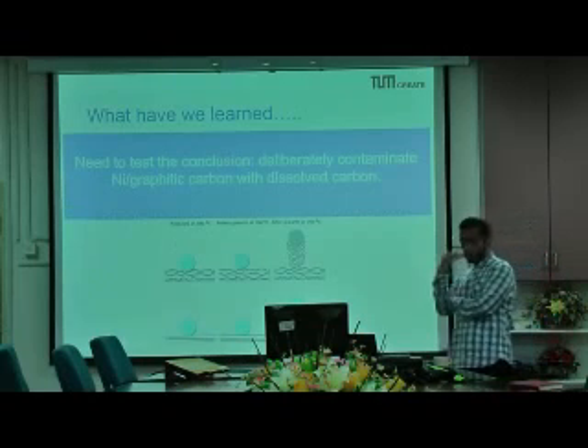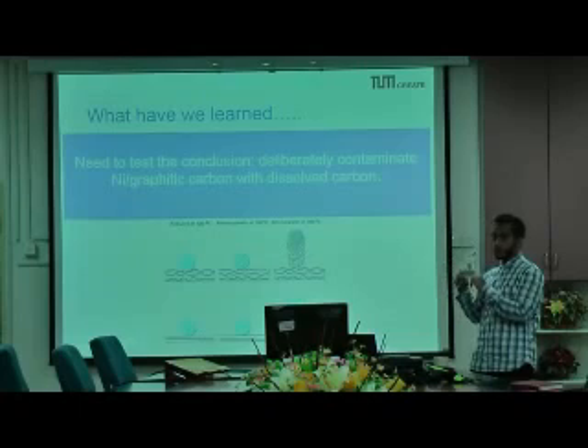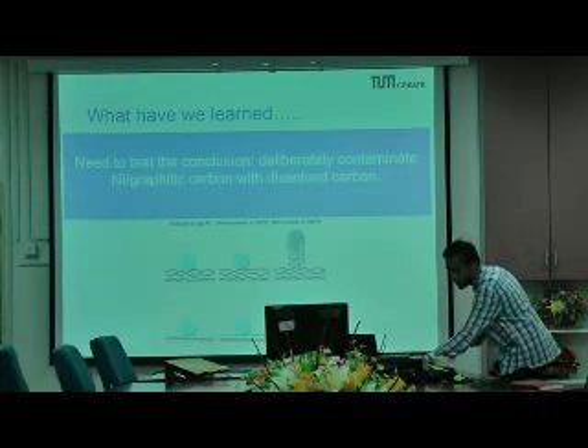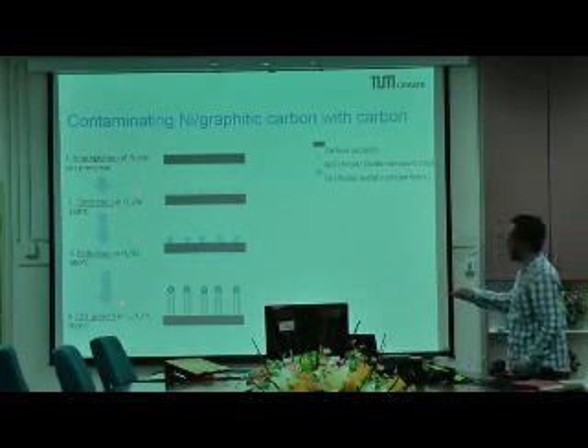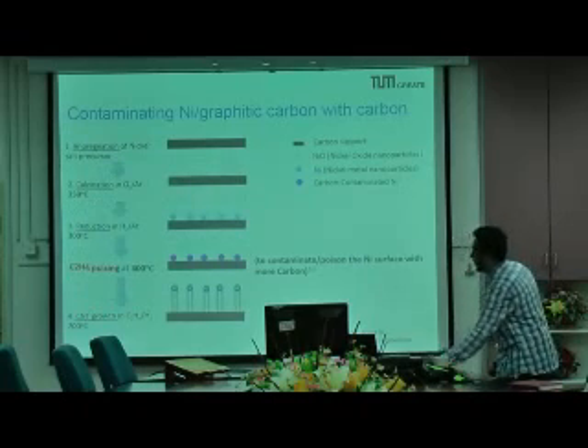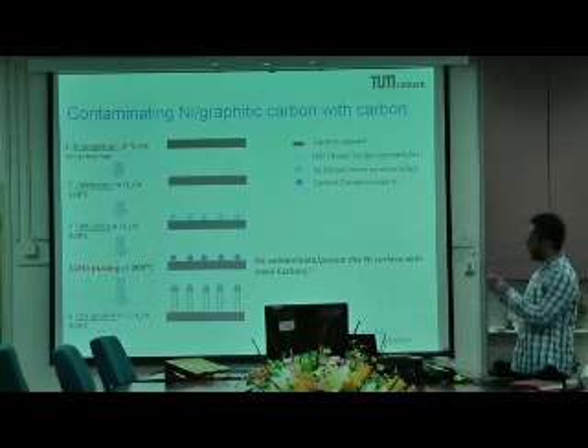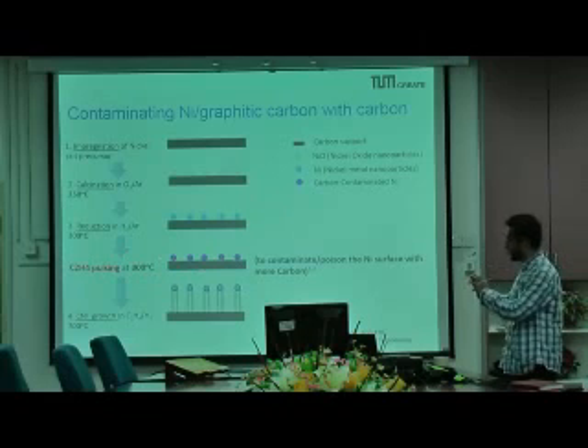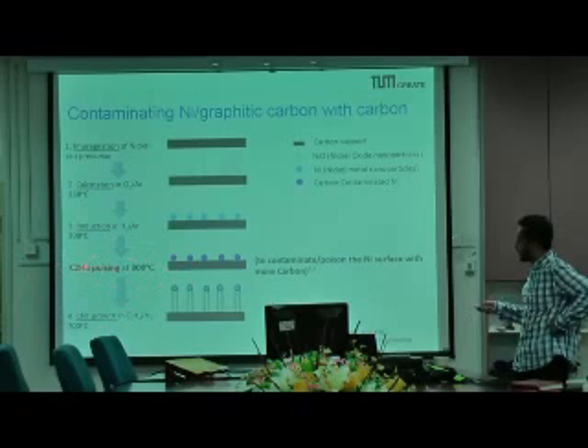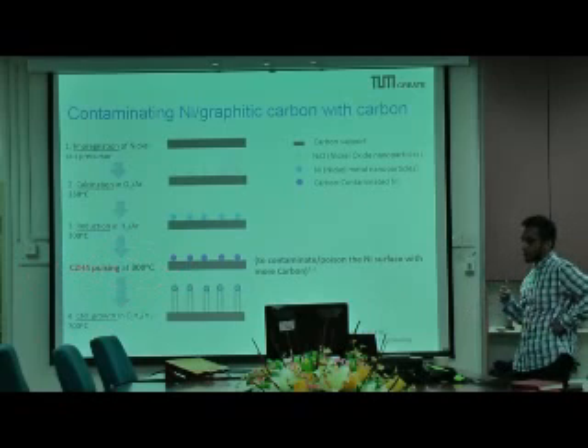So to test this, we have to somehow deliberately contaminate the graphitic nickel material with dissolved carbon. How do we do this? In the reaction step that I explained earlier, we have this reduction and calcination reaction. So we wanted to introduce a small amount of carbon onto the catalyst just before it grows. After reduction, we pulse the system with a small amount of ethylene at 300 degrees to contaminate the nickel iron particles with some amount of dissolved carbon. The reaction of ethylene at low temperature to create dissolved carbon has been documented in earlier works by Jacques.